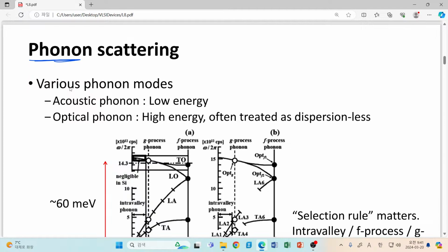However, due to thermal excitation, although the average energy is determined by the crystal structure, atomic cores can move slightly around their nominal position. That corresponds to phonon scattering, because atomic cores are in many cases charged. In this silicon case, we have to say that they are positively charged, and our electrons are interacting with them.